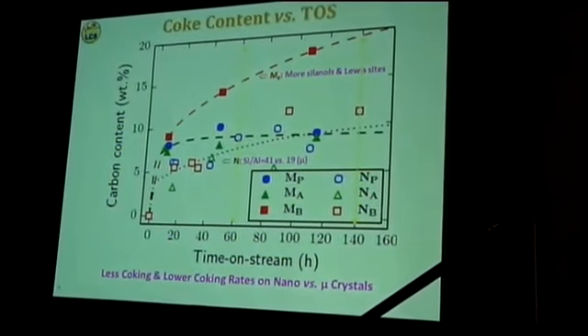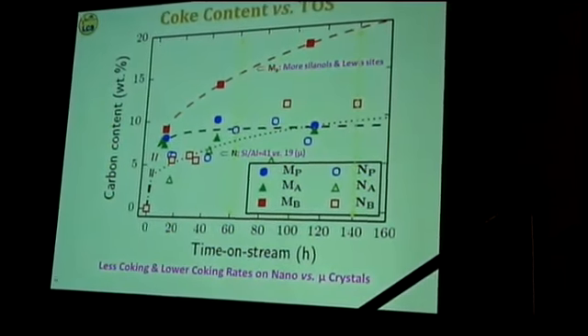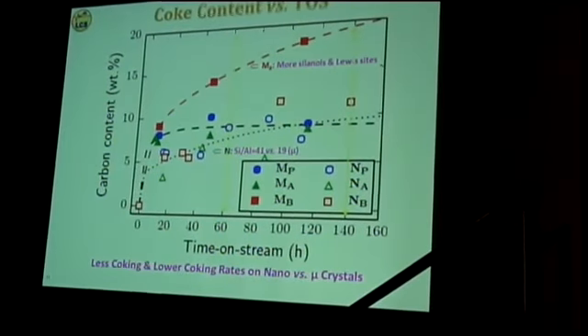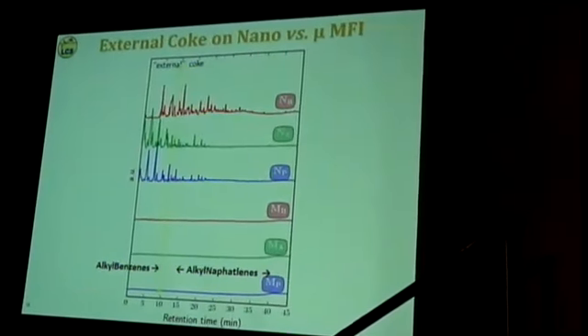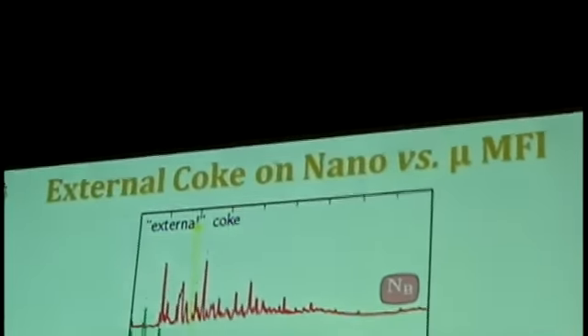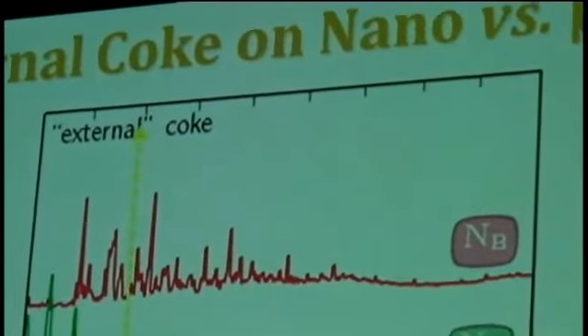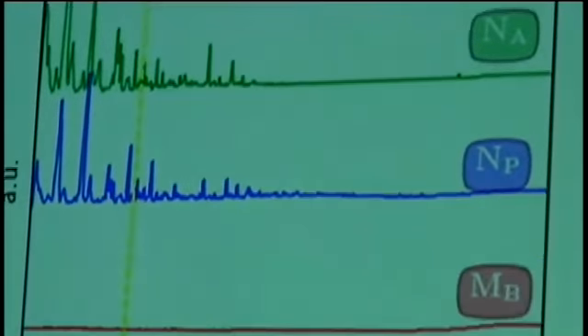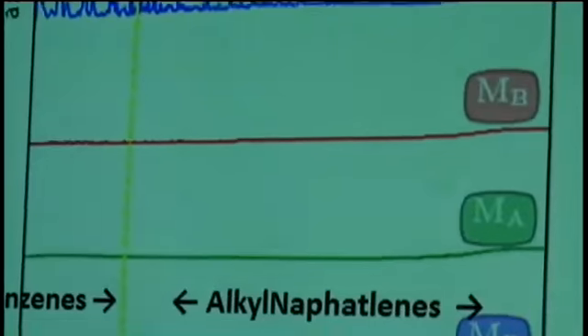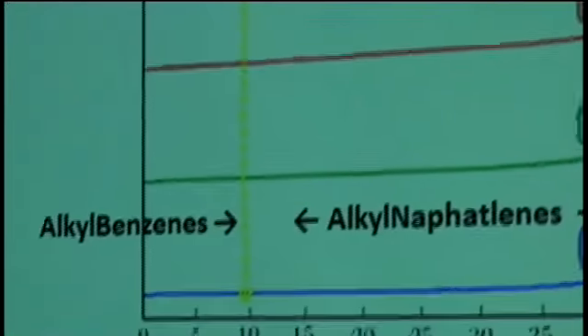So after knowing the level of coke, we are now going to look at what is on the external surface of the zeolite. And what is on the external surface of the zeolite is analyzed by GCMS. And basically we see two families of compounds. The first family of compounds are alkyl benzene, and the second family are alkyl naphthalene. This is what we call the external coke.